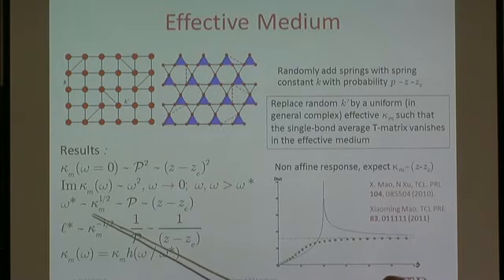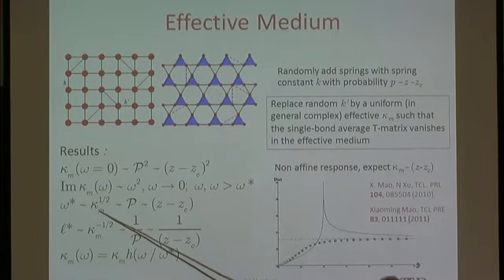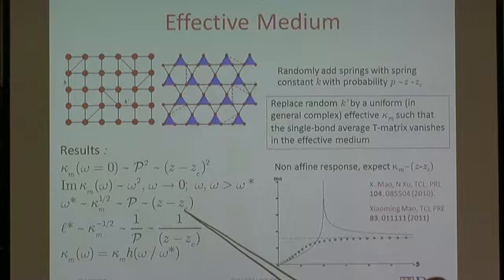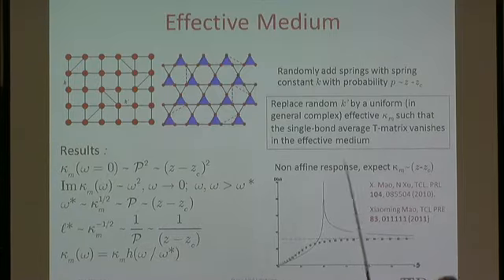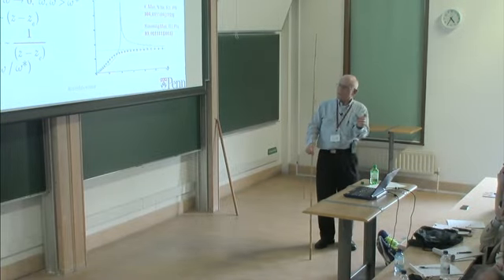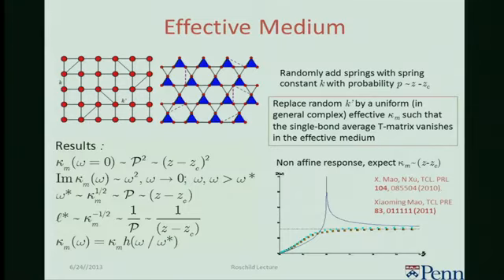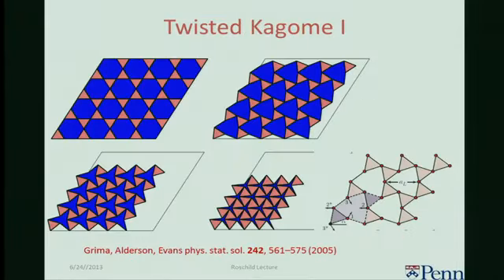And remember that now I have an effective medium, so the omega star is the square root of this next nearest neighbor effective spring constant. It goes like delta z. And the same thing for the length. So this effective medium then gives you exactly what you get for jamming when you scale things with delta z. Furthermore, the density of states for the non-random square lattice has a strong Van Hove singularity at basically omega star. You put in the randomness, and the density of states does exactly what you got for jamming. So this clearly has many of the properties of jamming, and one can explore that further.